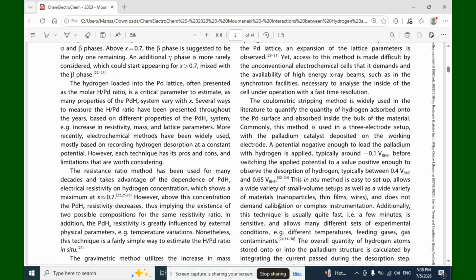necessary to analyze the inside of the cell under operation with a fast time resolution. The coulometric stripping method is widely used in the literature to quantify the hydrogen absorbed onto the palladium surface and inside the bulk of the material. Commonly, this method is used in a three-electrode setup with the palladium catalyst deposited on the working electrode. A potential negative enough to load the palladium with hydrogen is applied, typically around -0.1 V RHE, before switching the applied potential to a value positive enough to drive the desorption of hydrogen, typically between 0.4 V RHE and 0.65 V RHE.